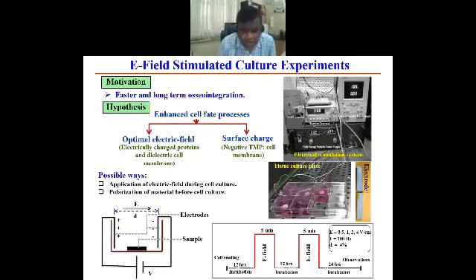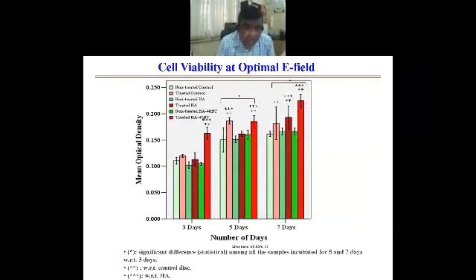And then we innovated how this electric field is delivered to the biomaterials in the culture solution. Initially, we did incubation for 12 hours, followed by electric field stimulation for 5 minutes, then a 12-hour rest period with simple culture without electric field stimulation, then again 5 minutes. We do it that way for a few days in culture, and thereafter we looked at cell viability using the MTT assay.